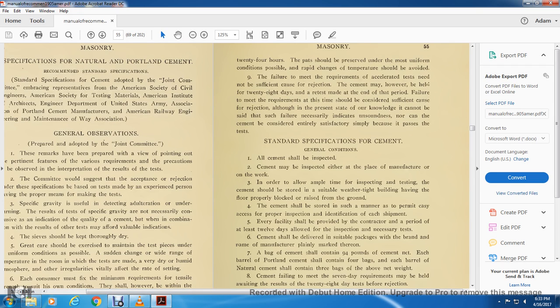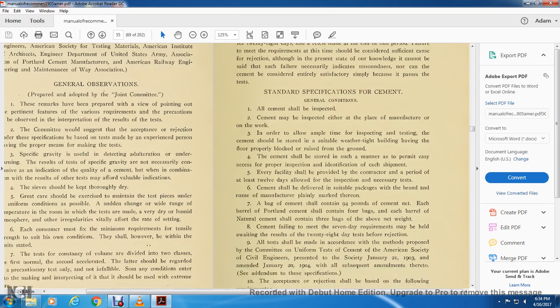24 hours. The pat should be preserved under the most uniform conditions possible. Rapid changes of temperature should be avoided. The failure to meet the requirements of accelerated testing is not sufficient cause for rejection. The cement may, however, be held for 28 days and retested at the end of that period. The failure to meet the requirements at this time should be considered sufficient cause for rejection. Although in the present state of our knowledge it cannot be said that such failure necessarily indicates unsoundness, nor can the cement be considered entirely satisfactory simply because it passes the test.